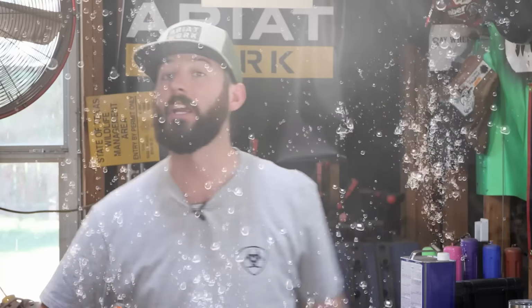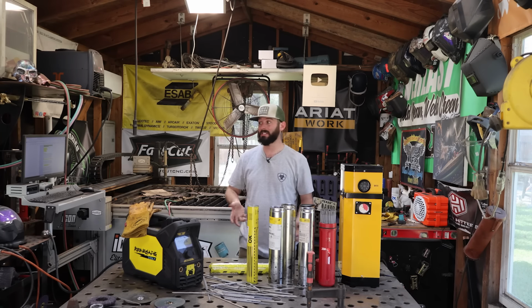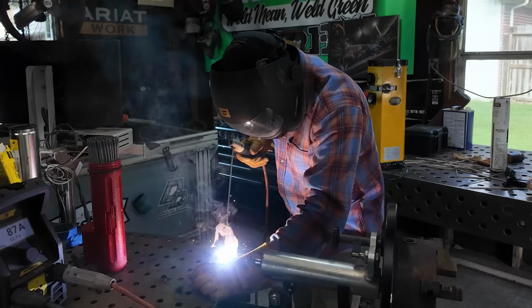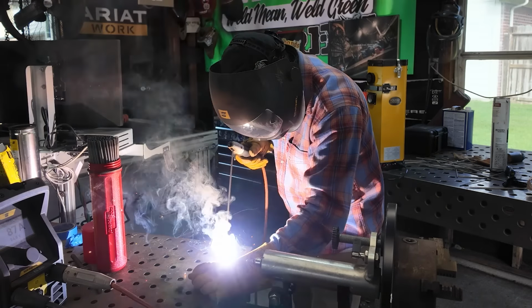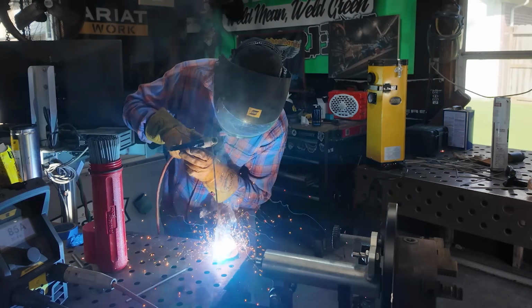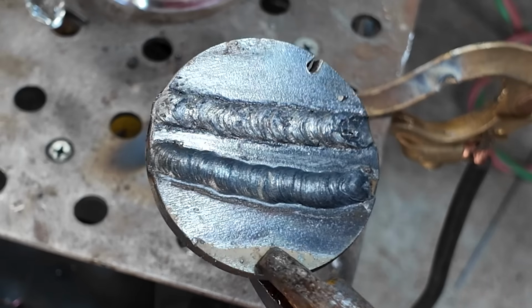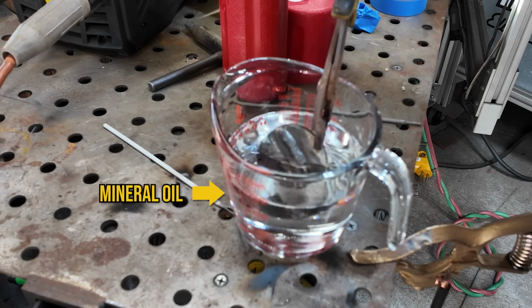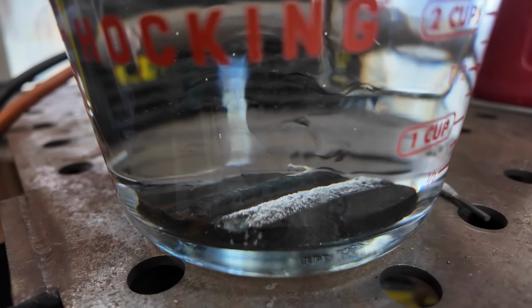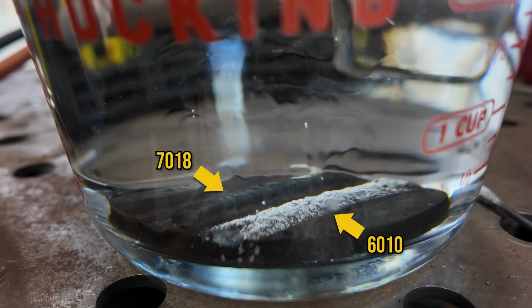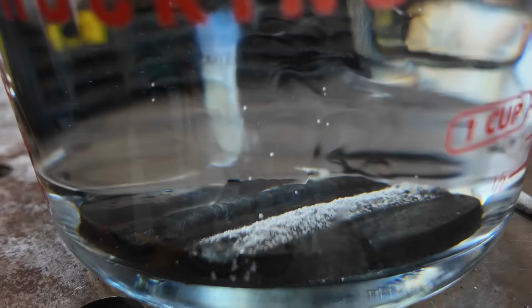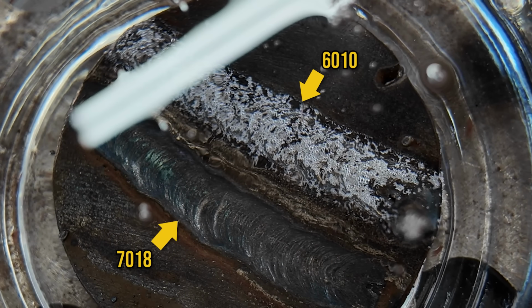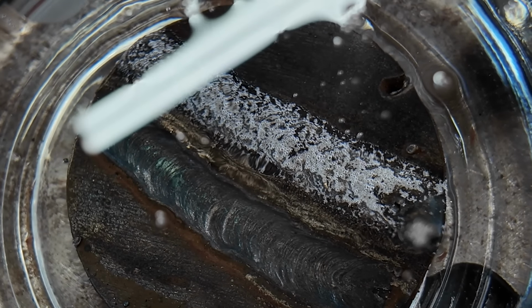I live in Houston, Texas. It's all around me. I'm swimming in moisture right now. And that hydrogen likes to escape out of the weld. The best way I can show it is submerging a 7018 weld that I welded next to a 6010 weld that I welded on this little puck that I went ahead and dipped in mineral oil. You can see almost immediately a reaction with the 6010 where all these bubbles start to come out. And that's that hydrogen trying to escape that weld so quickly, whereas you see the low hydrogen weld doesn't have any at all. That's the whole point.